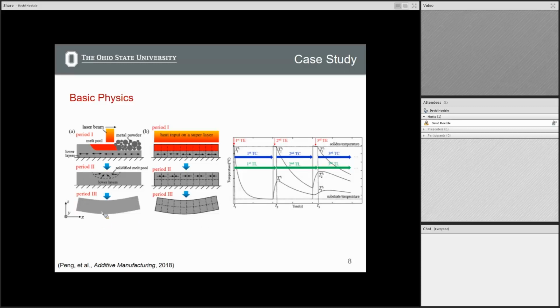Okay. And so this is a very sequential operation, where if I wanted to look at what is the temperature at any point in the part, I have melting and then I have cooling happening continuously. So if I look at T1 here, it corresponds to the first layer of material being deposited. I have heating up to the melting point, or the solidus temperature. It then cools down. And then my next layer comes on top of it, and because the layer above it is hot, it's heating up my first layer. So my first layer is cycling through all these different temperature profiles.